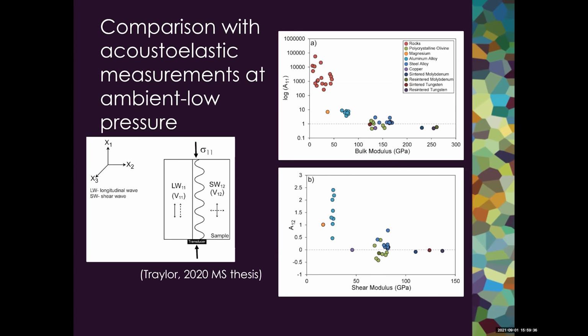And it isn't that surprising that the polycrystalline olivine samples are plotting with the metallic materials rather than these rock studies. This is mainly due to the fact that the acoustoelastic response for geologic materials at ambient to low confining pressures is attributed to pore closure and microcracks, which should not be as significant at our high confining pressure conditions. And so we can see that there's a clear relationship between these acoustoelastic constants and other material properties.